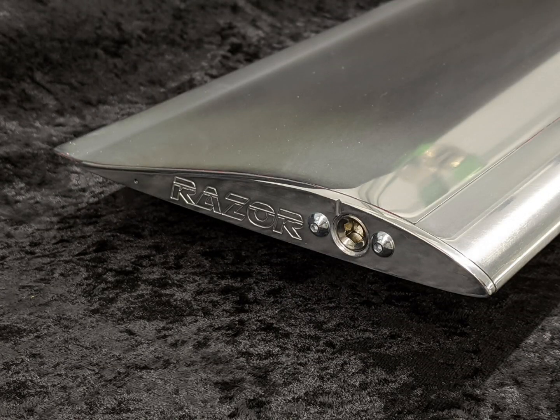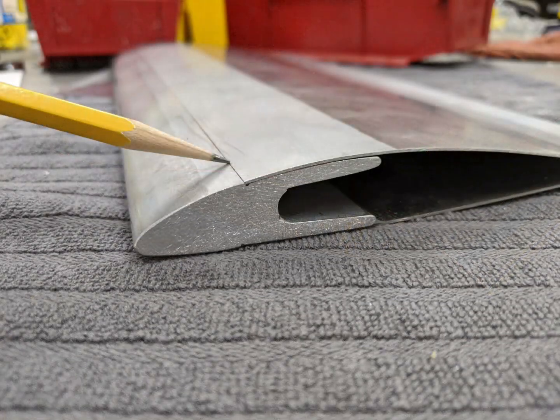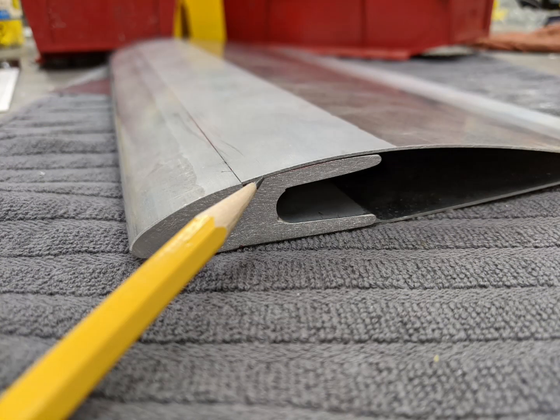The one problem area is the transfer from the extrusion to the front edge of the top skin. This is hard to get a smooth transfer without applying an excessive amount of force to get the edge tucked down in there. And by applying an excessive amount of force, a high pressure area would be created in this zone, which would push out much of the adhesive in this critical area.